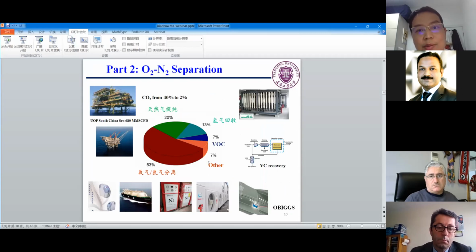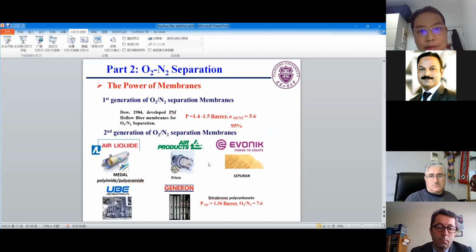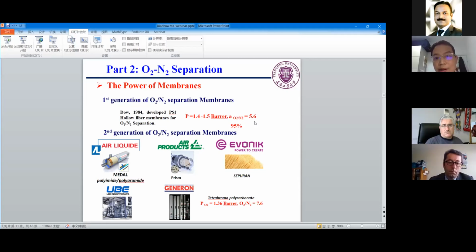We are very interested in the O2/N2 separation because it takes up more than half of the gas separation industry. However, as we know, all membrane separations rely on the membranes. We can see the power of the membranes. This is the first generation of the O2/N2 separation membranes. It was reported by Dow Company in 1984. It was based on polysulfone with the permeability of oxygen about 1.4 to 1.5 barrer, and the O2/N2 selectivity 5.6. But this kind of membrane can only separate O2/N2 and enrich the nitrogen to about 95%. So it's not economic, it's not competitive.